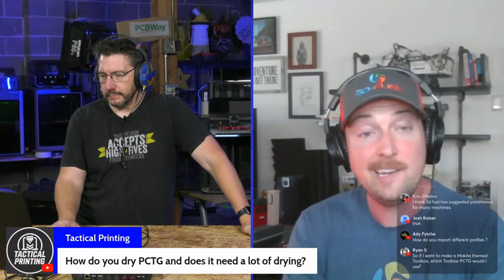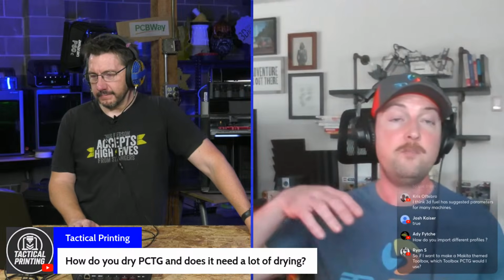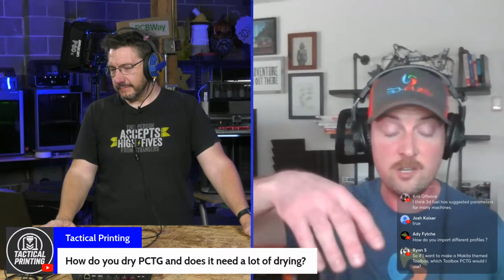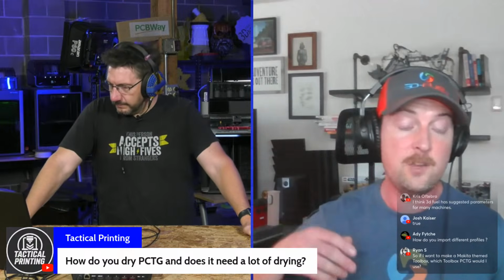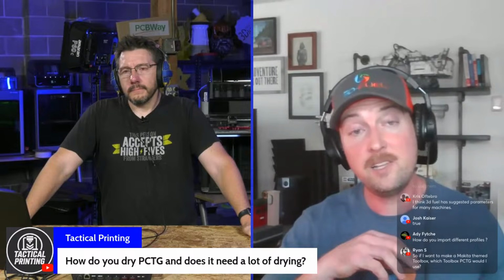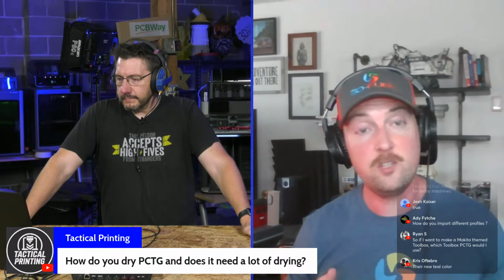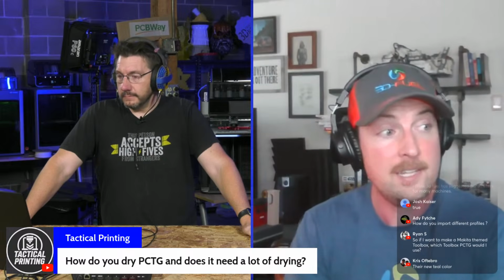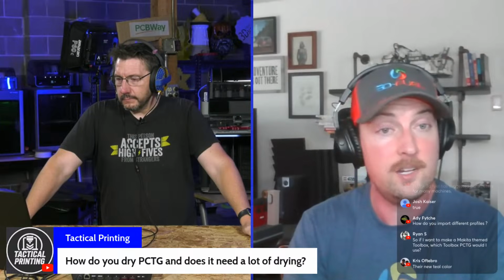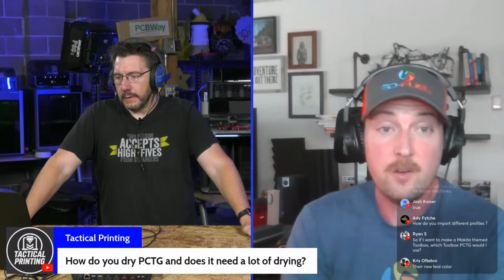Okay. And it can be impacted by the humidity in the environment where it's being dried. And not all filament dryers are made equally. That's the absolute truth. When we're making the filament in our facility, we dry our resin in a desiccant wheel dryer. So think of desiccant that is continuously being recharged. You have hot air blowing through one part of it as it's continuously rotating, that recharges the desiccant and dries it out. Then the air that runs through the hopper for the plastic pellets is running through the desiccant that has just been dried. So it's perfectly dried desiccant. Wow. And we dry it at 65 degrees Celsius for 4 to 6 hours, but that's with very, very dry air running through it. So you are in a very arid environment.